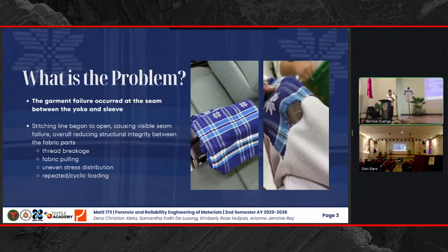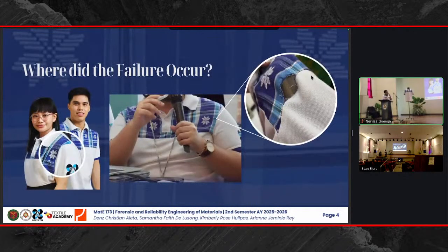So our client reported a recurring mechanical failure in one of their official uniforms. Specifically, the seam between the front yoke and the sleeve has opened, leading to visible separation. So the client hypothesized that this could stem from thread breakage, fabric pulling, uneven stress distribution, or cyclic loading during wear. So here is a more detailed look of the said failure.